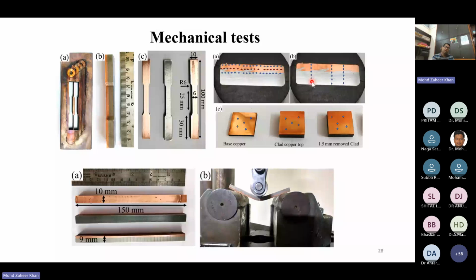Similarly, more micro hardness was carried out on the base copper. Then micro hardness was carried out on the top surface of the copper plated, and then another set of micro hardness was taken after removing the top 1.5 millimeter layer of the clad surface. Several indentations were taken and the hardnesses were reported.